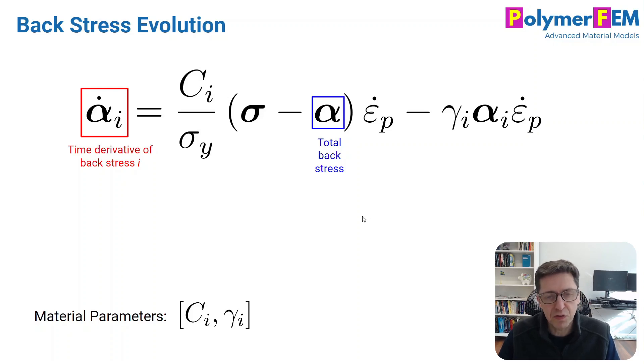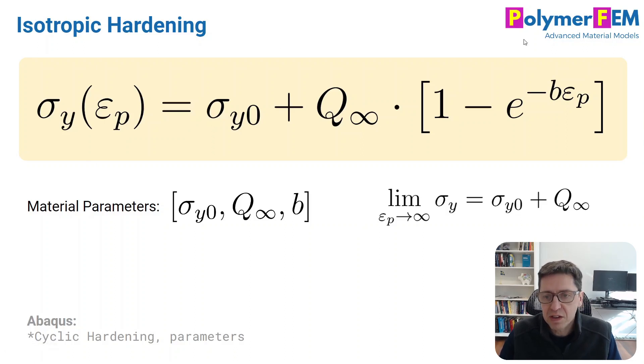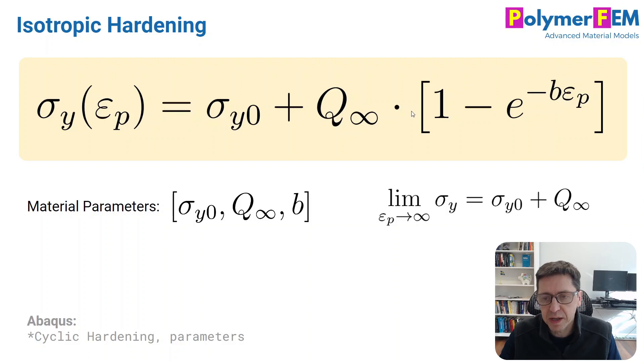At the same time you often introduce isotropic hardening. In Abaqus, this can be specified using the cyclic hardening keyword, which activates an equation showing how the yield stress evolves with plastic strain using an initial constant sigma_y0, a saturation parameter q_infinity, and a rate parameter b. In the limit as plastic strain goes to infinity, the yield stress approaches the initial value plus the saturation limit q_infinity, and the rate at which it approaches this value is given by b.